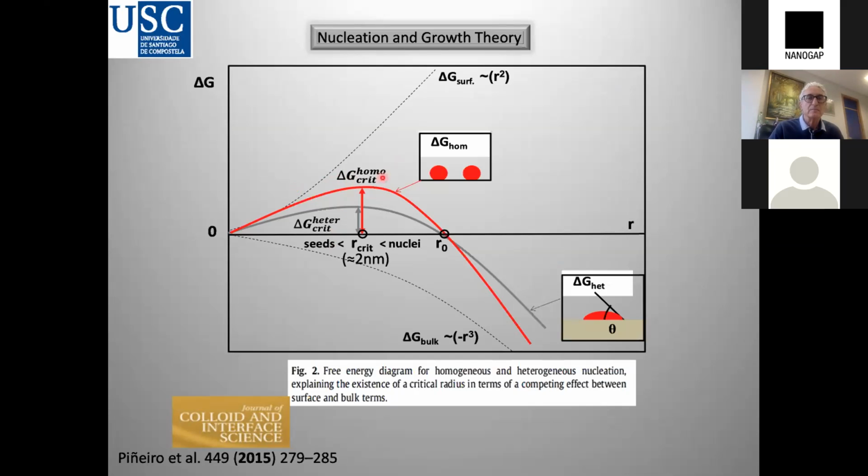You have to consider that when a nanoparticle is formed in a solution, there is a change in the phase, because you have initially a liquid phase and then you change to a solid phase. So you have to create an interface, and this has a curvature at the beginning. The curvature is very high, and you have to consider that for the formation of the new phase, you have to put in energy to create this interface. This is related to the interface tension, and this has to be overcome before the formation of the nanoparticle.